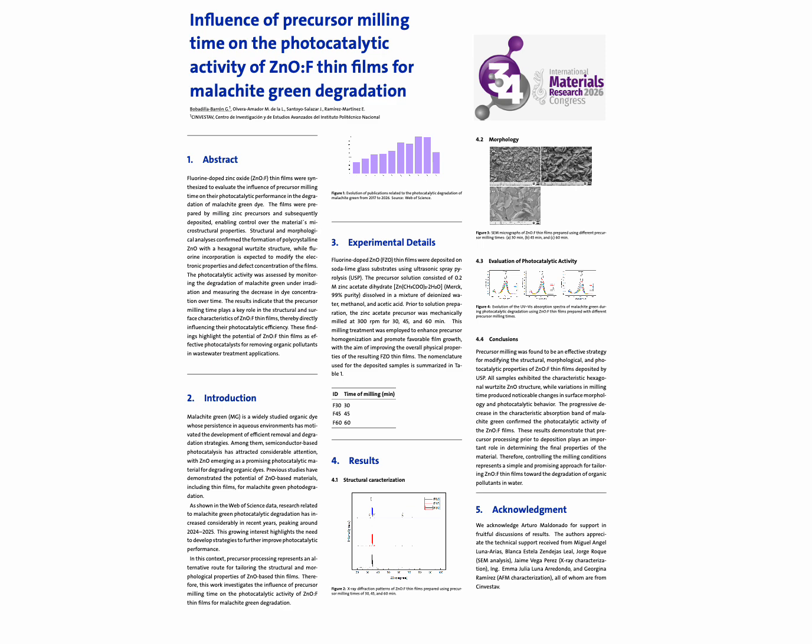In conclusion, we demonstrate that precursor milling is a simple strategy for tailoring the properties of these films deposited by ultrasonic spray pyrolysis. All samples maintain the characteristic hexagonal wurtzite structure of ZnO, while changes in milling time produce noticeable differences in surface morphology and photocatalytic behavior.